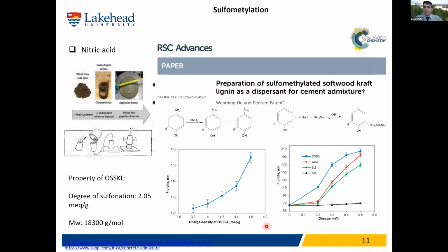For the cement admixture, again, lignosulfonate has been used for this application. We wanted to make sulfomethylated lignin that has similar properties to lignosulfonate, but we couldn't just sulfomethylate lignin. We saw some difficulties. So first we oxidized the sample to open up the structure, and then we did the sulfomethylation. What we noticed was that by increasing charge density of the product, we got much better fluidity. I will talk about fluidity in a second. And the performance of our product was much better than, again, the two different lignosulfonate samples that are available in the market and are claimed for the same purpose.